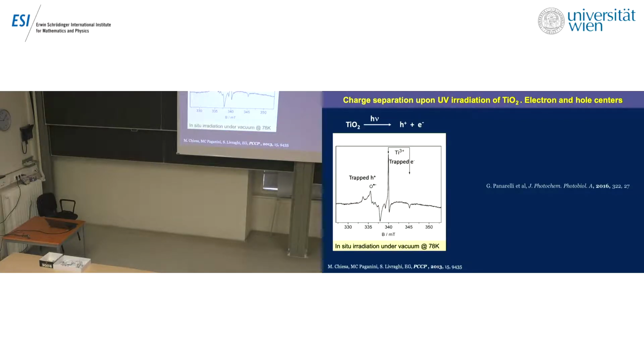As it has been told yesterday and during this conference, one of the possibilities to generate polaron pairs is irradiation. This is what occurs, as observed by EPR in the case of titanium dioxide, this is anatase, irradiated with UV light. Once again, we are lucky, since it is normally very difficult in EPR to have resolved that situation. It's not NMR, unfortunately for us. Okay, but here is the trace of the hole polaron, and here is the trace that I will discuss in the following of the electron polaron.